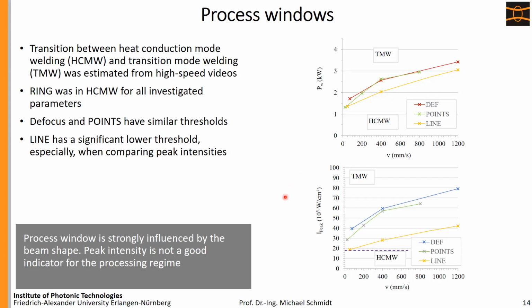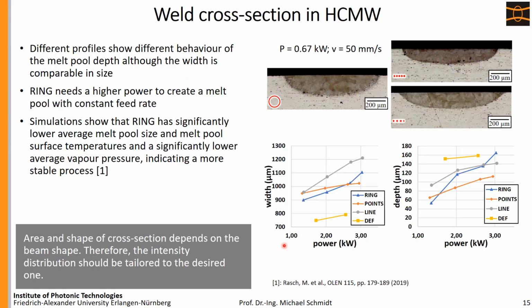But what this also shows is that the process window is very strongly influenced by the beam shape, and as soon as we leave intensity distributions like Gaussian or top hat, naming the peak intensity is no longer a good indicator for the processing regime. So as soon as we start with beam shaping, we need other parameters to describe what's going on. But this is only a side thing I wanted to say.